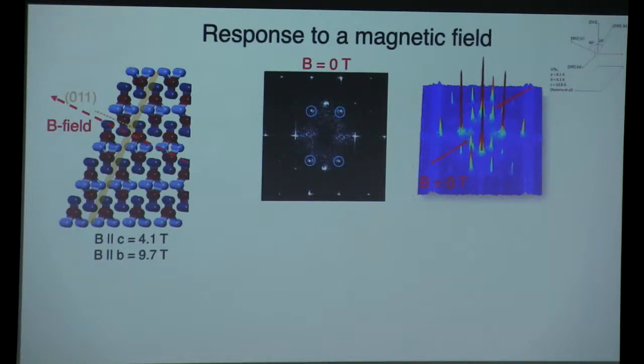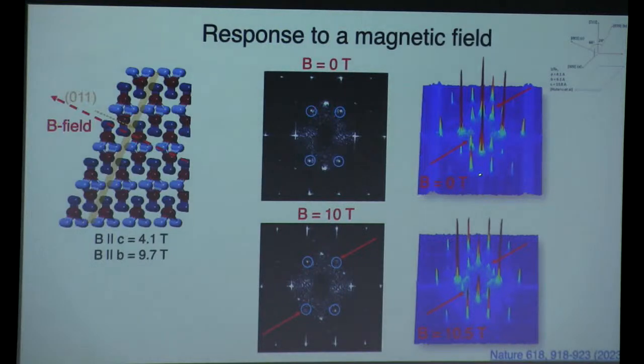Now let's turn on a magnetic field, and what you find is that first, all 3 peaks are suppressed. This one and this one, they're all suppressed. You can even compare these 2. The second thing is that one of these is much more suppressed than the other, and it's actually almost completely gone. The suppression of this charge density wave is a huge surprise, because that's not expected for a normal charge density wave. But that one being suppressed more than the other is not surprising, because a magnetic field breaks mirror symmetry in any case.